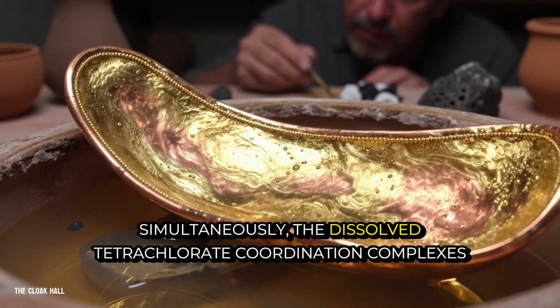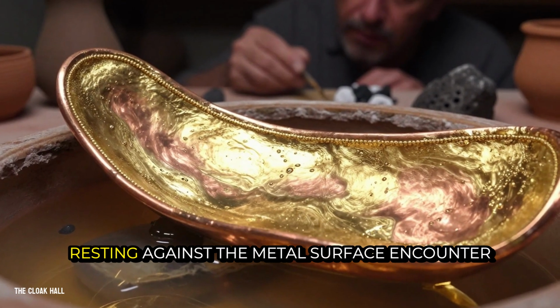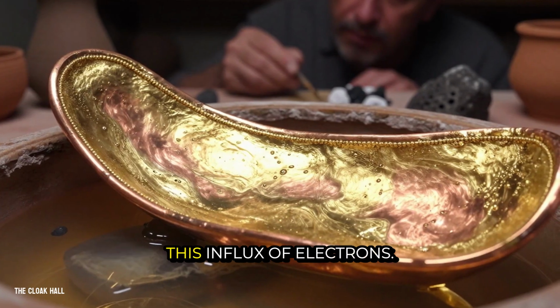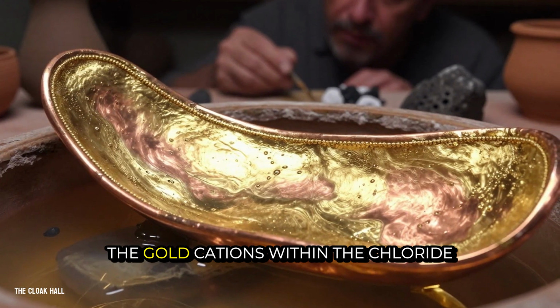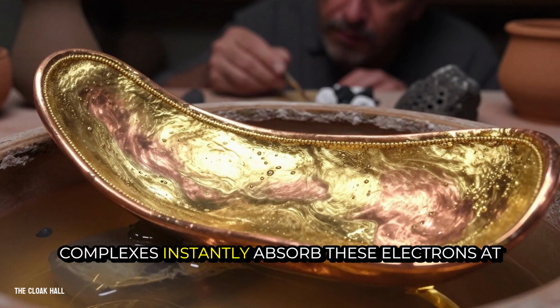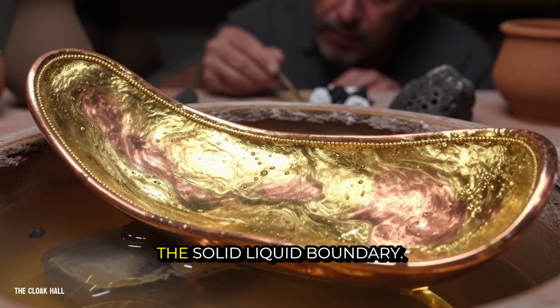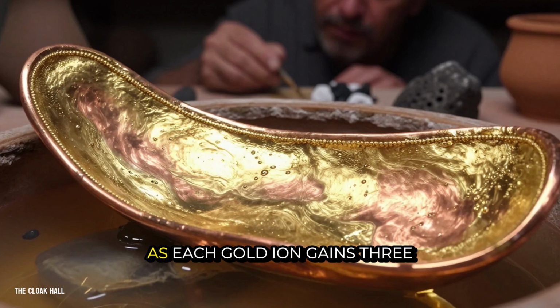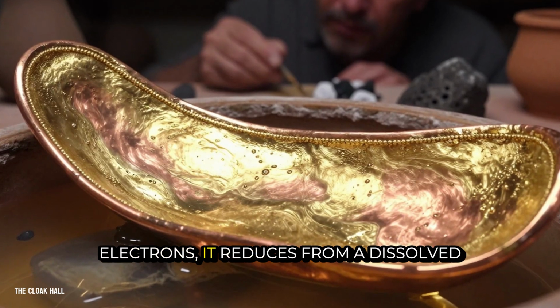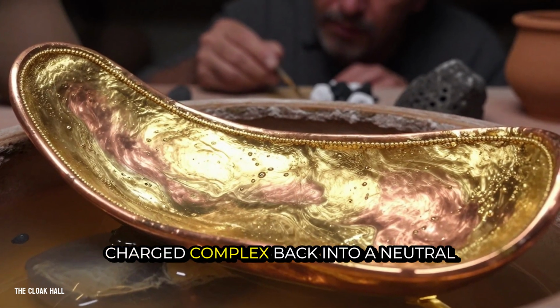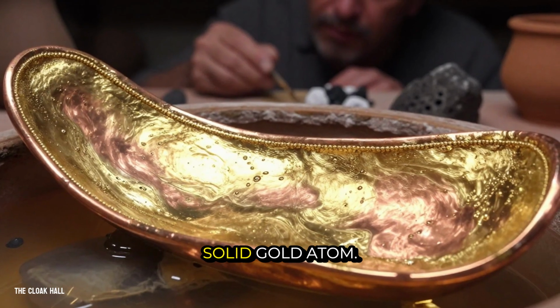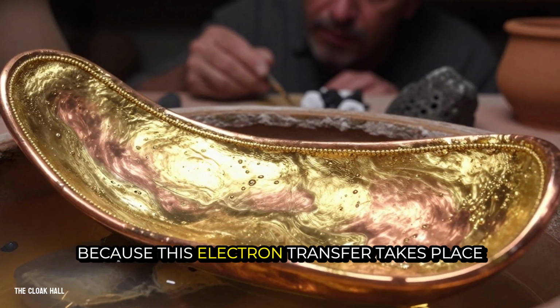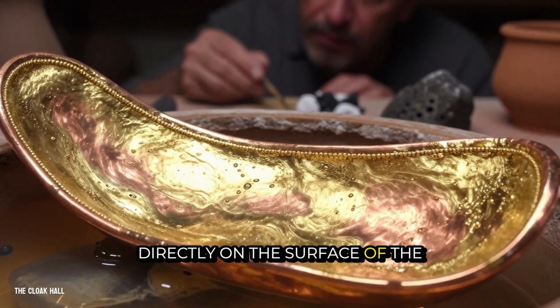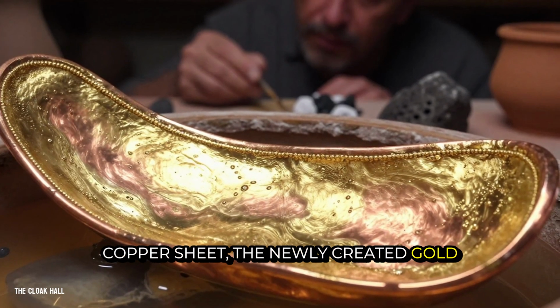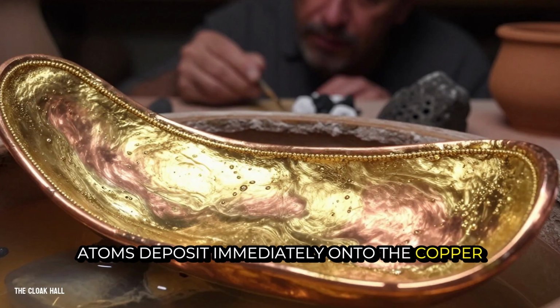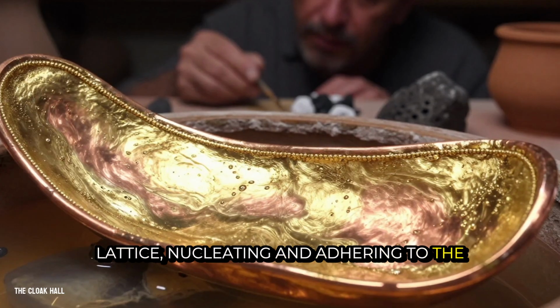Simultaneously, the dissolved tetrachloroaurate coordination complexes resting against the metal surface encounter this influx of electrons. The gold cations within the chloride complexes instantly absorb these electrons at the solid-liquid boundary. As each gold ion gains 3 electrons, it reduces from a dissolved, charged complex back into a neutral, solid gold atom. Because this electron transfer takes place directly on the surface of the copper sheet, the newly created gold atoms deposit immediately onto the copper lattice, nucleating and adhering to the metal.